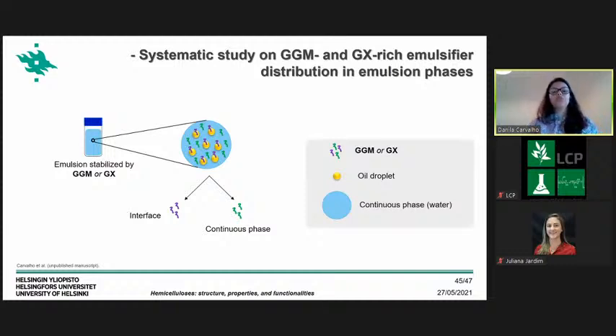The first answer was the nature of the interaction between cellulose and lignin. And you could see that at least part of the lignin was covalently linked to the hemicellulose. And the other is how this GGM and GX really act in the stabilization of the emulsion. So what we did in the continuation was prepare an emulsion using the samples, some of the fractions that we prepared, and then later recover the GGM and the GX from the interface. The interface here is the one that is adsorbed on the oil droplet. And then we also collected the GGM and GX that were unadsorbed in the continuous phase, which was the water.